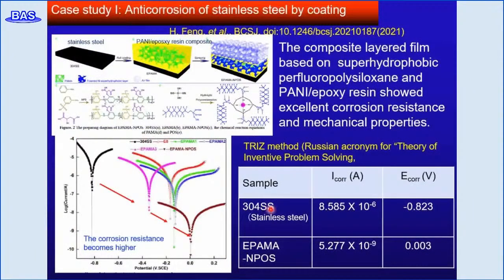Here is a case study of anti-corrosion of stainless steel by coating from the literature. The corrosion potential of bare stainless steel on the Tafel plot was shown in the black line, and the corrosion potential is minus 0.823 volt.